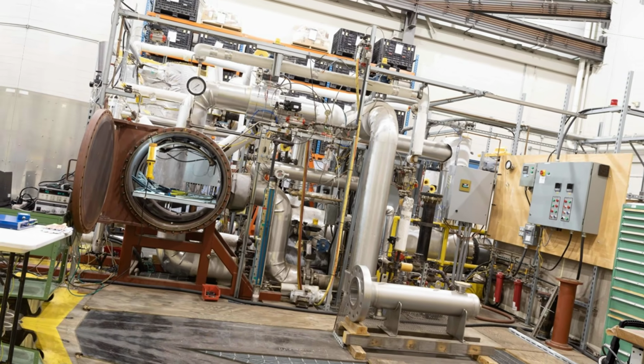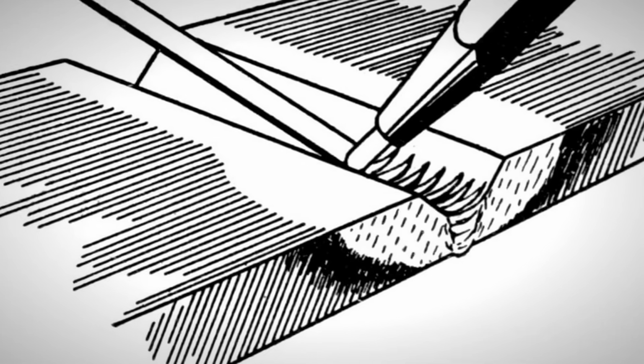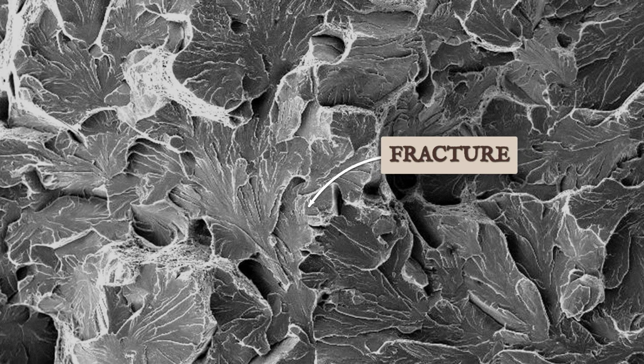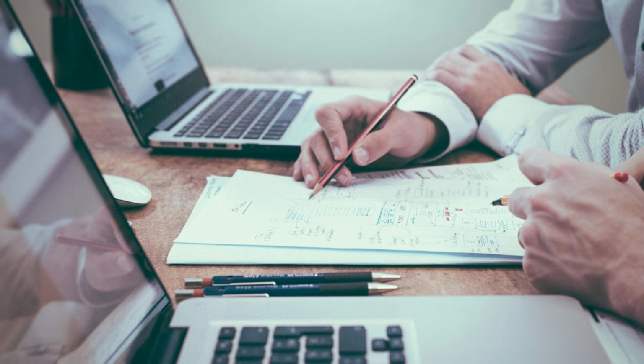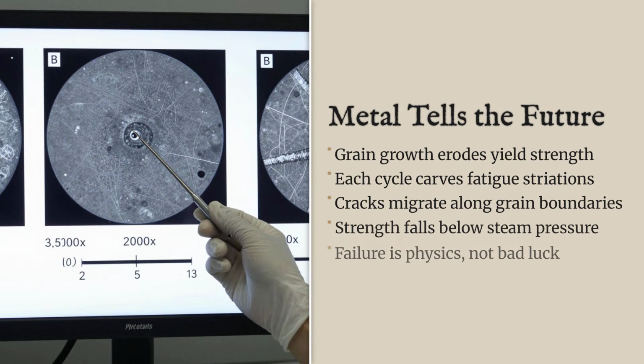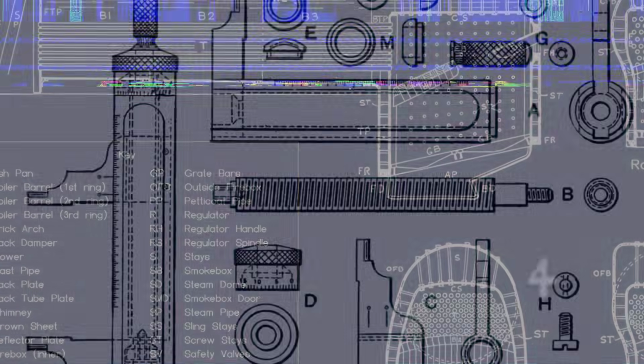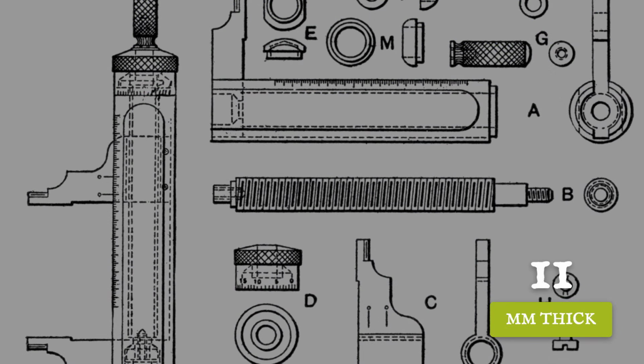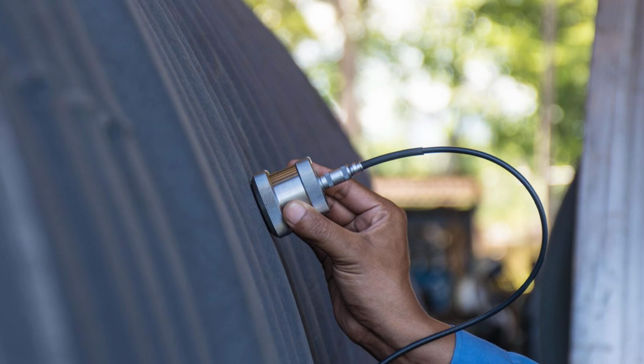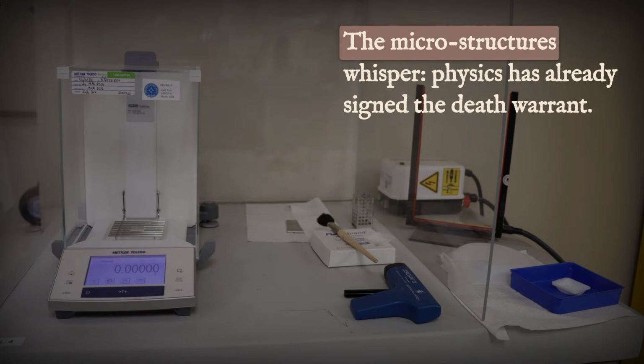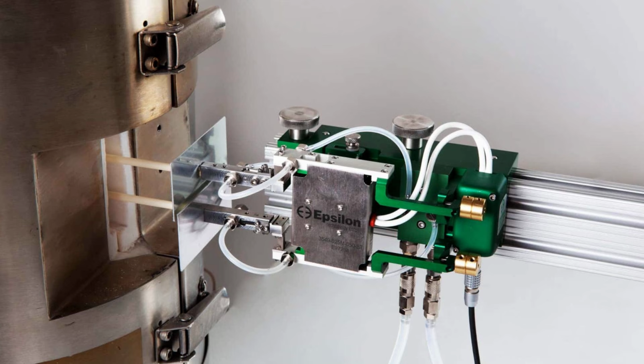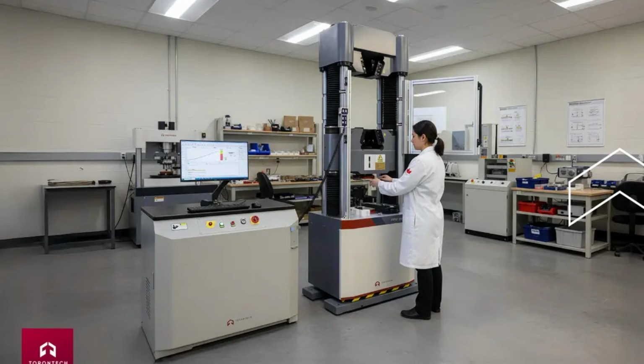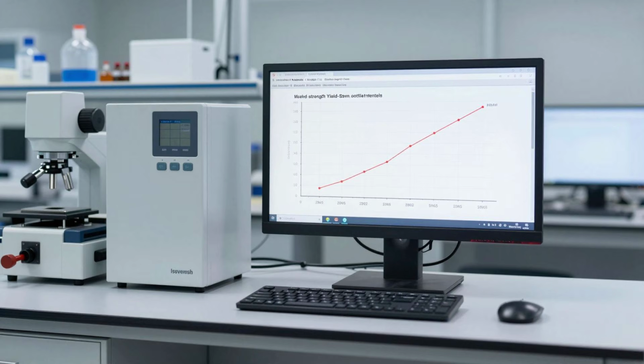Photographs from the lab show the story in sharp relief. A staybolt snapped at the shank, the grain torn open by repeated overload. The metallurgist's notes are blunt: thermal softening, fatigue striations, intergranular failure. The crown sheet above it is warped, the steel thinned to 11mm at the center. Ultrasonic scans reveal pitting from acidic condensate, each pit a stress riser waiting to finish the job. The numbers are clinical. Yield at 400 degrees Celsius is 150 megapascals. At 550 degrees Celsius, it is 90.